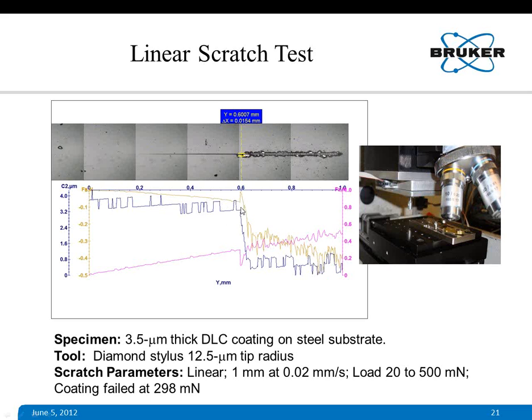During the scratch, we measured in situ the Z encoder, and you see the Z encoder plot shows there is a coating depth of about 3.5 micron at the point of failure. The sample is mounted on the stage. The tip is here. The tip comes here automatically on the script. You just specify what to do, scratching or image scratching. It scratches, and the optical head actually moves automatically to the place where this scratch exists, and it takes a series of pictures, collates all these pictures together, and plots them with the Fx and Fz data automatically.